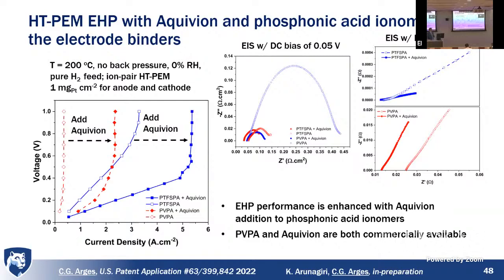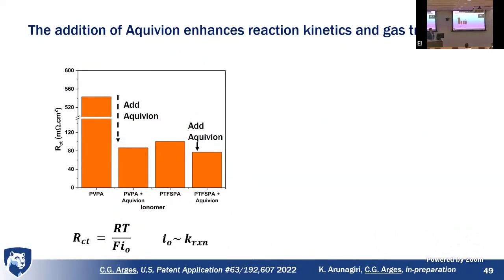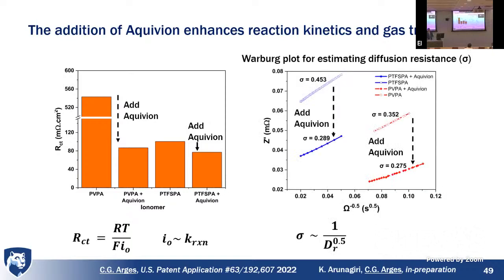So these are Nyquist plots where we looked at the MEA. And the thing is, when we add Aquivion to the phosphonated ionomer, we see a reduction in charge transfer resistance for both the systems. It's a lot more for this commercial polyvinyl phosphonic acid than it is for this polytetrafluorostyrene phosphonic acid. So the addition of this binder material is not just enhancing conductivity, it is enhancing reaction kinetics.